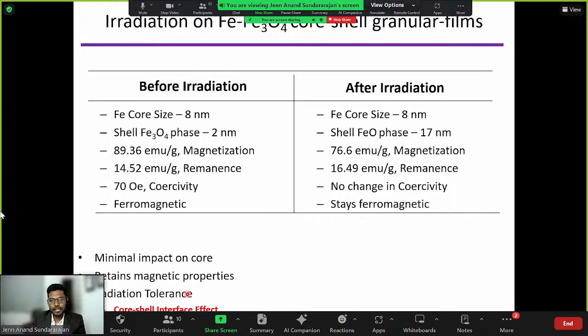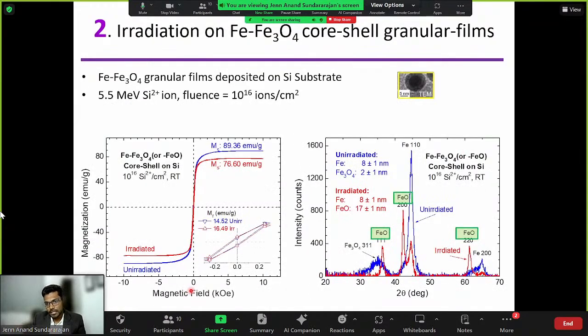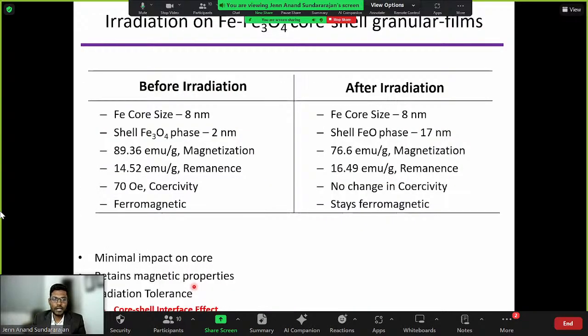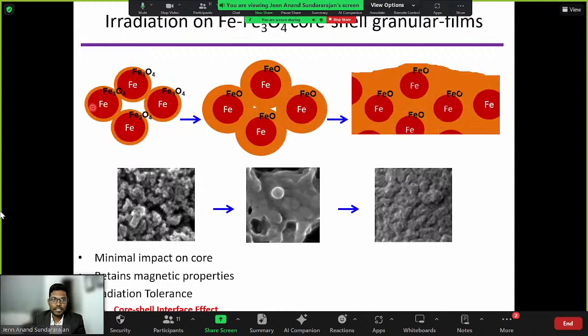This shows that the material is very robust and stable to irradiation because of the core-shell interface effect and grain boundary effect. That's what I want to talk about, because the core is retained, and we know it has a lot of grain boundaries, and also core interface effects. If you look at the outset, this is what has happened. Eventually, the outside structure changed from Fe3O4 to FeO, but the core is still retained because there is no change in the core, and it starts to form something like this on the material, as you can see from the picture here.